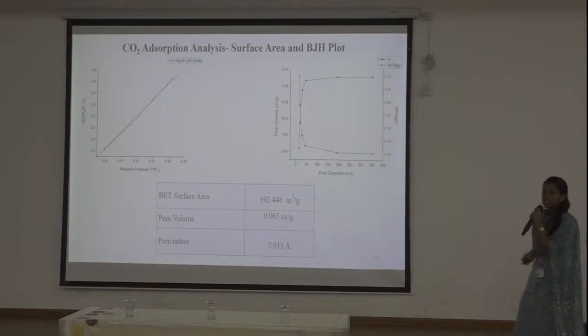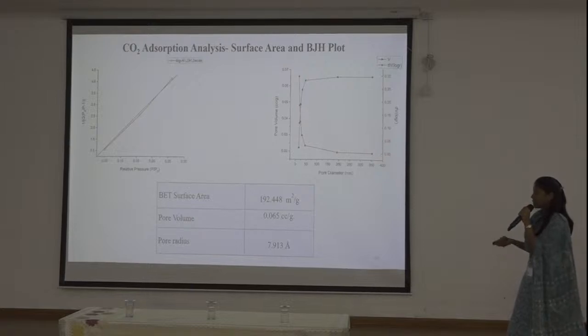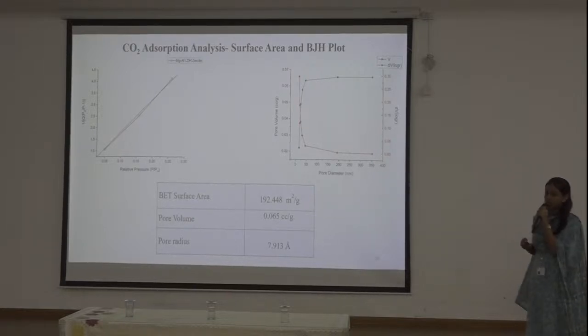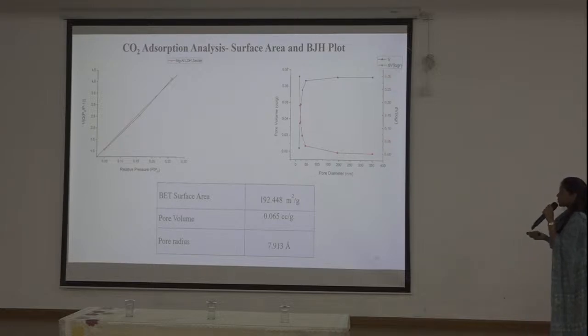The CO2 adsorption analysis was calculated for the material, and the BET surface area was found to be around 192.44 meters square per gram. We achieved a pore volume of 0.065 cc per gram, and a new pore radius better than the previous LDH, at 7.913 Angstrom.